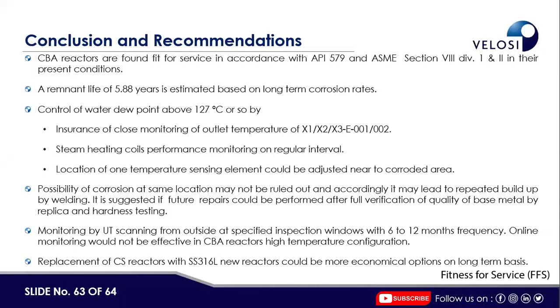The location of one temperature sensing element could be adjusted near the corroded area, which is basically the 12 o'clock location of the reactors. The possibility of corrosion at the same location may not be ruled out, and accordingly it may lead to repeated build-up by welding. It is suggested that future repairs be performed after full verification of the quality of the base metal by replica and hardness testing. Monitoring by UT scanning from outside at specified inspection windows with 6 to 12 month frequency. Online monitoring would not be effective in the CBA reactors' high temperature configuration. Replacement of CS reactors with new SS316L reactors could be a more economical option on a long-term basis.